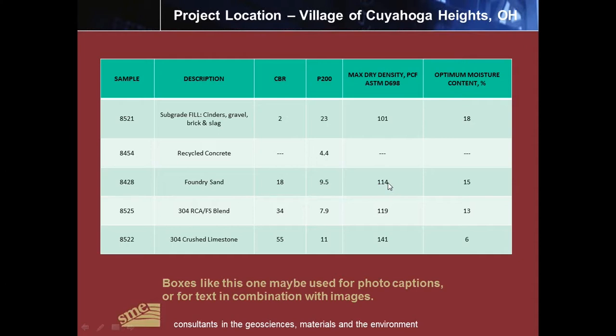It also had a little higher maximum density than normal, which is normally about 109 pounds, and our optimum moisture content was slightly higher than what we typically see for a lot of foundry sands. Our blended aggregate, the 304 recycled concrete with the foundry sand, had a CBR of 34, P200 of about 8%, density of 119, with an optimum around 13.